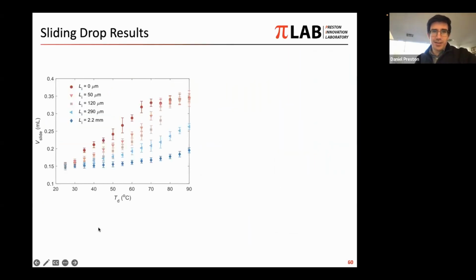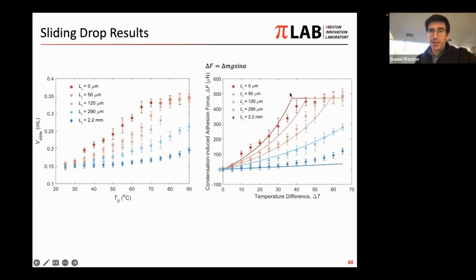And I'm going to go back to the experimental results here. So these are the sliding volumes at departure. We can convert these over to some delta F, some change in adhesion force. And we can plot this along with the model that I just described. And we get what I would say is a pretty good agreement between the model and the experimental data when we look at this adhesion force.